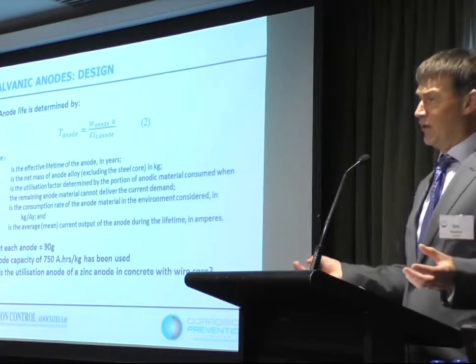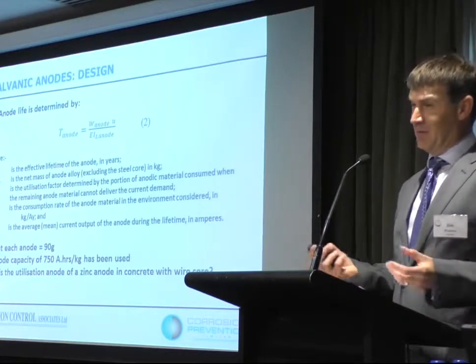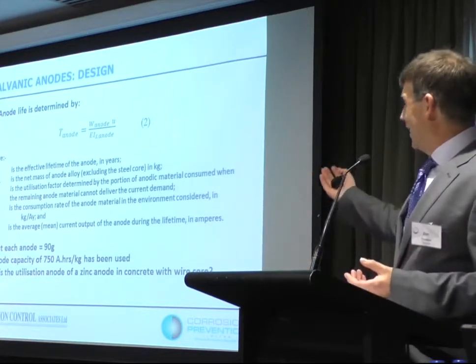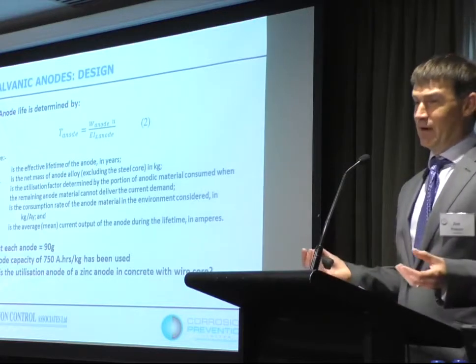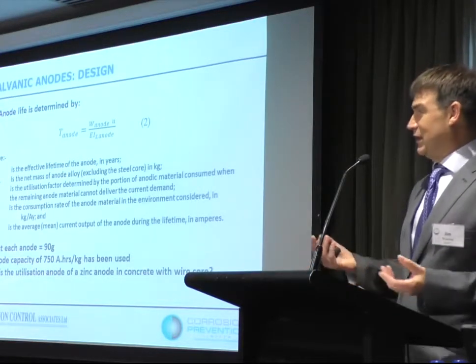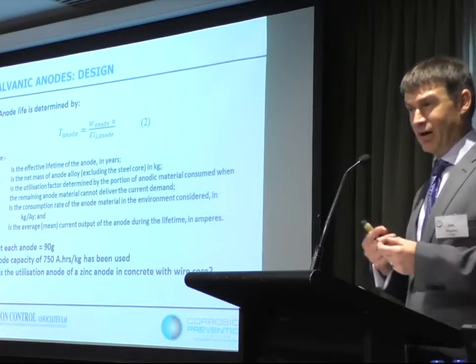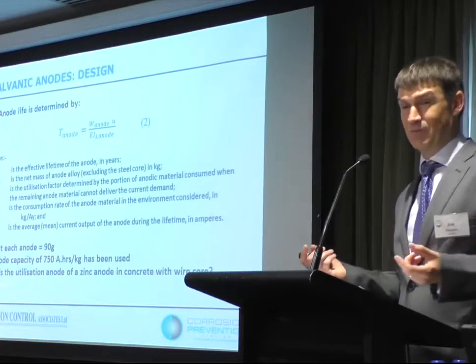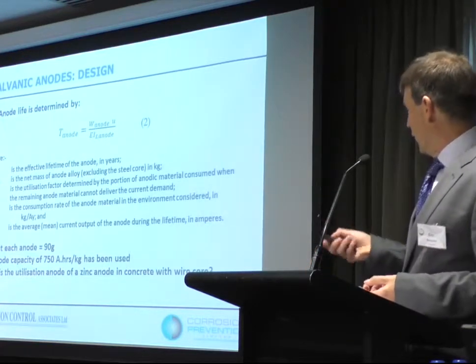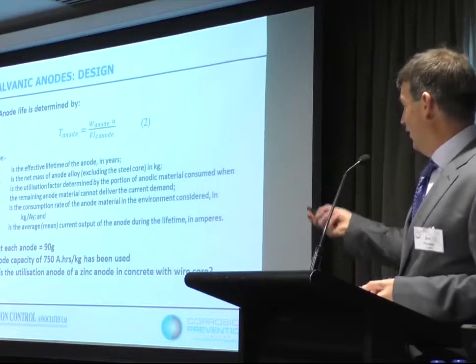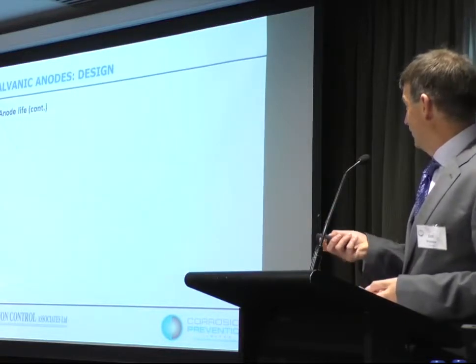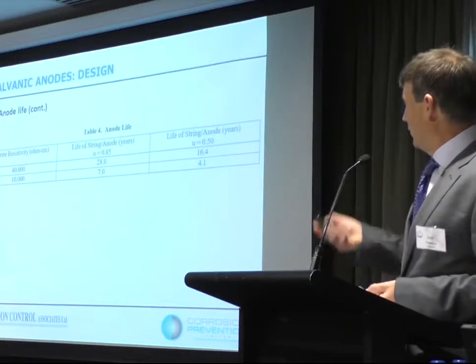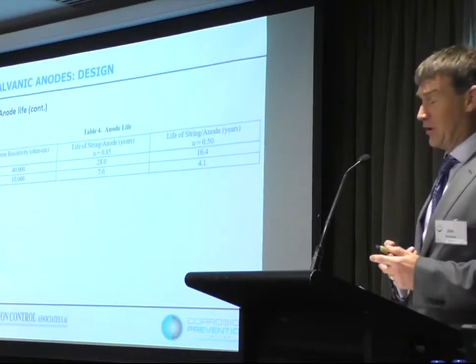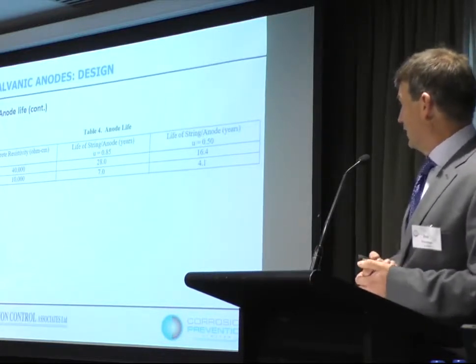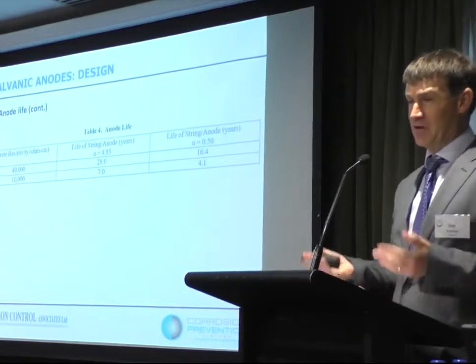There is no data at all for galvanic anodes in concrete. Do they last for 85%, which is normal for a galvanic anode in the sea or the ground, or is it less than that? Because they've only got a small wire tie that attaches the zinc to the reinforcement. We know what the weight of the anodes are. We know what the anode capacity is. So we picked two utilization factors just to compare it. A fairly standard 0.85, but we think that might be generous.